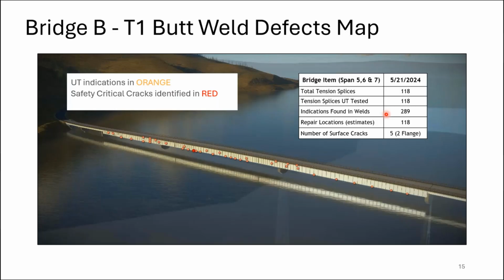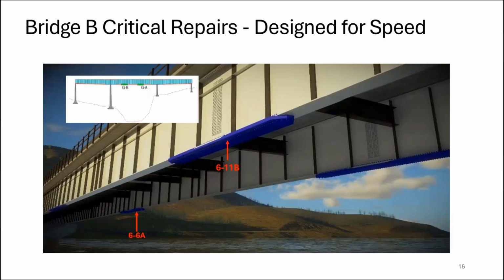The other cracks, because hydrogen cracking happened shortly after fabrication, it was determined that these indications had been there from the beginning of the bridge, and that it could safely handle local traffic once these surface breaking indications were addressed. So the critical repairs were addressing these 2 cracks on the 2 girders in the cantilevered span and the hanging span between the 2 pin and hangers. And they were designed to fabricate, install, and reopen the structure as quickly as possible. So they were really designed for speed.